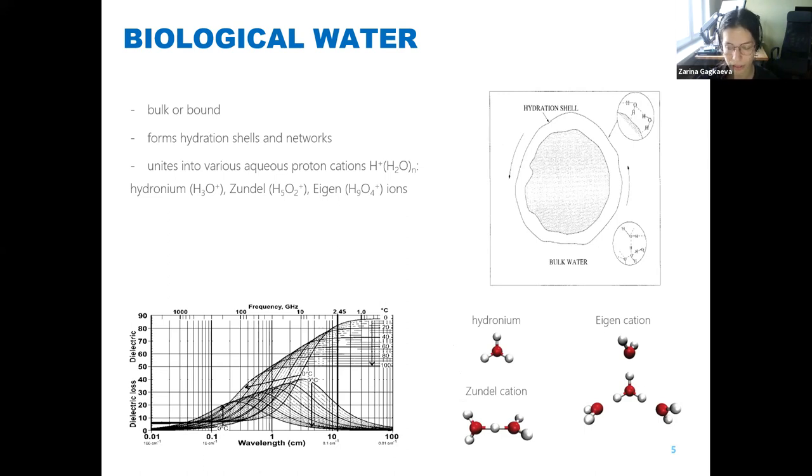In various condensed media including biological materials, in the broadband dielectric spectra, water manifests itself as a Debye relaxation in the gigahertz terahertz frequency range with the frequency lowering while the boundness of water increased.